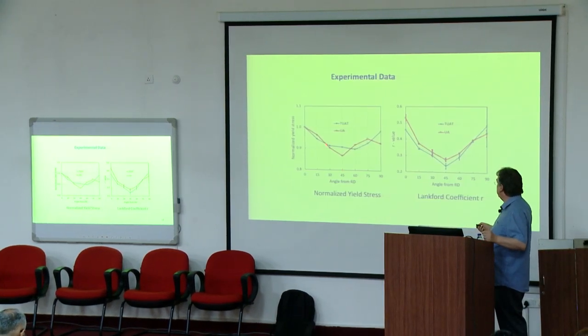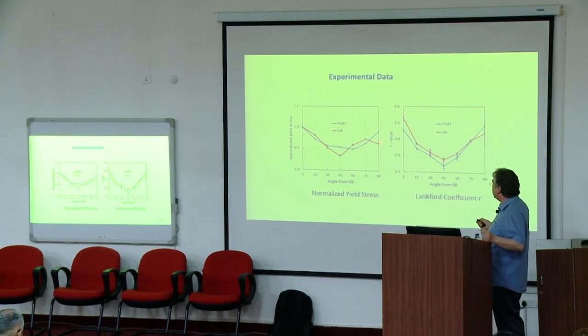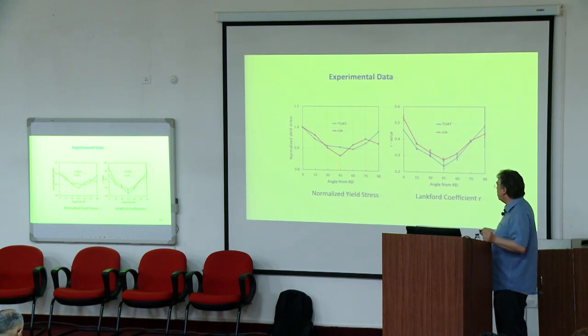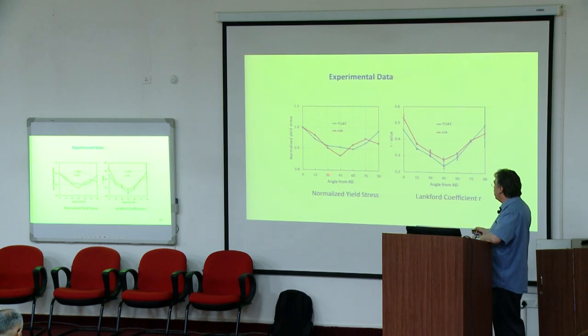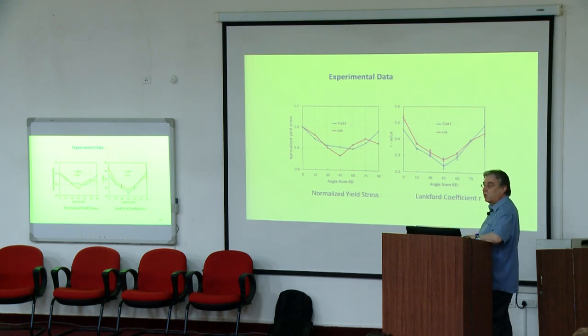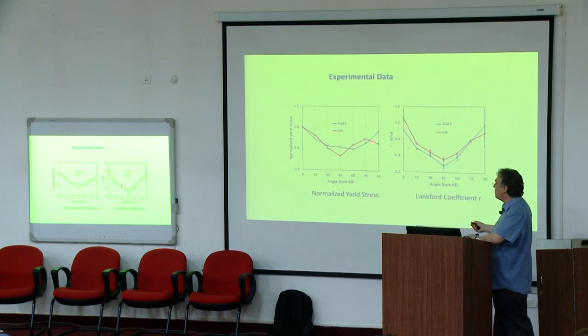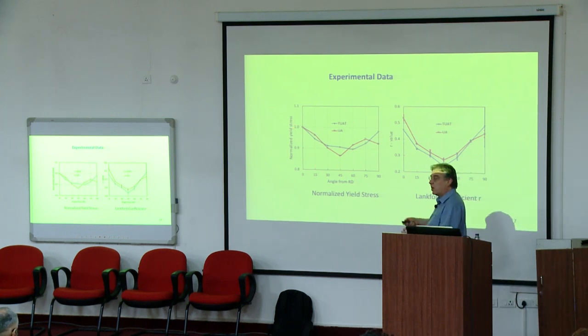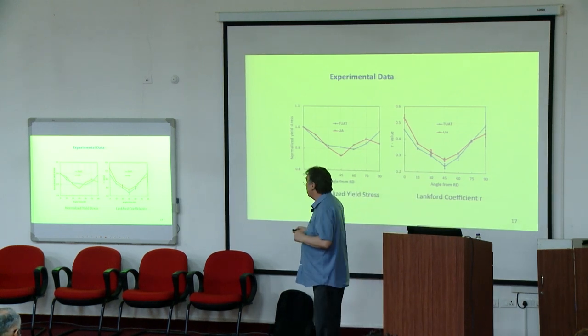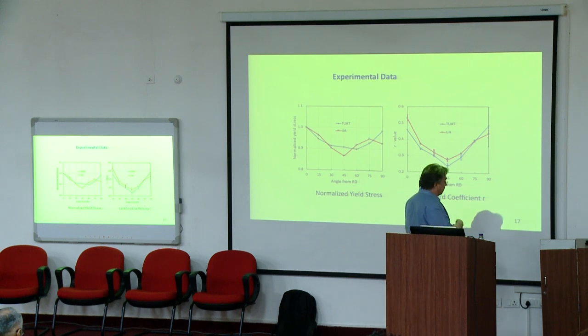Here, these are experimental data. These are data of the normalized yield strength and anisotropy. These were measured at two different universities. So you have a typical U-shape evolution. Here, this is the angle with respect to the rolling direction. So these are all the results of a tensile test, and this is the yield strength in the rolling direction. This is the yield strength in the transverse direction. This is the yield strength under 45 degrees and under all other orientations. Of course, because of orthorhombic sample symmetry, we only have to look between 0 and 90 degrees, between the rolling direction and the 90 degrees direction.